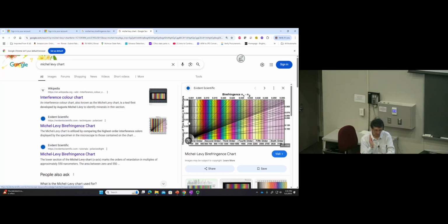Again, before you stretch, the sample is isotropic. So on the average, these two indices are the same. But as soon as you start to stretch, you cause the orientation of the electric field in the light to rotate. And the rotation gives you a projection into the horizontal direction, so light passes through.